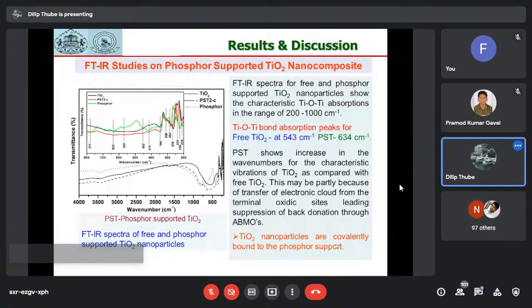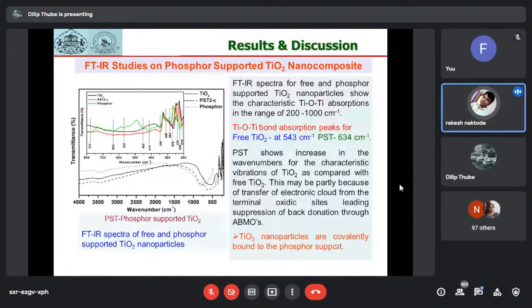So it is clearly visible that Ti-O-Ti bond absorption peaks are present in the region of 400 to 600 for free TiO2. This is present at 543, whereas in phosphor supported TiO2 material, it is found to be shifted to 634 centimeter inverse. This indicates that TiO2 particles are not only adsorbed on the surface of the phosphor material. They have bonded chemically on the surface of the phosphor material, and therefore during the photocatalysis, these bonds could not be broken.